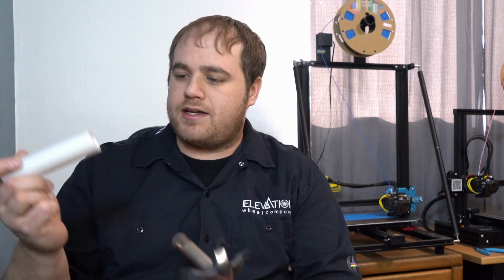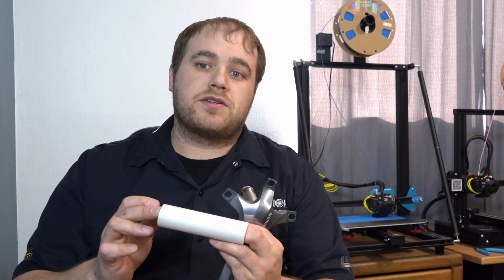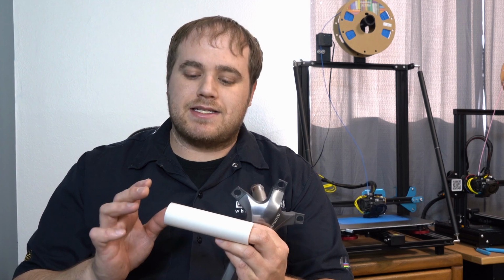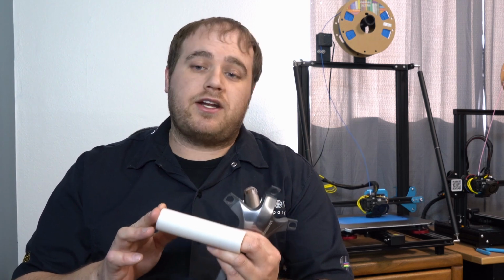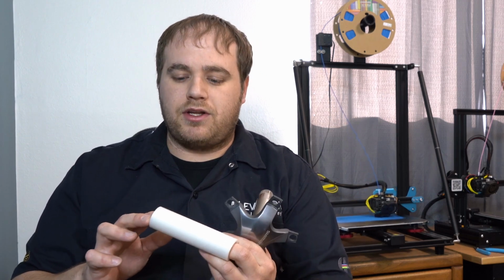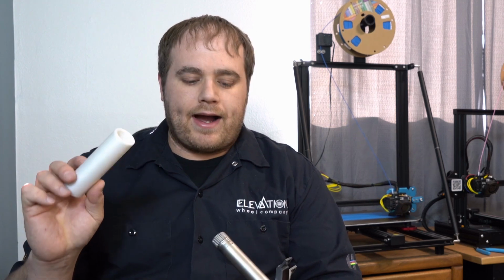This filament is a bit special as well. It's polypropylene filament, which also is completely resistant to sulfuric acid. So if you try to do this yourself, make sure you look at the filament you're using. This was the only one I could find that actually claimed to be stable in sulfuric acid. All the usuals like PETG, ABS, ASA, PLA, none of those would hold up in sulfuric acid. So that's how I found polypropylene filament.